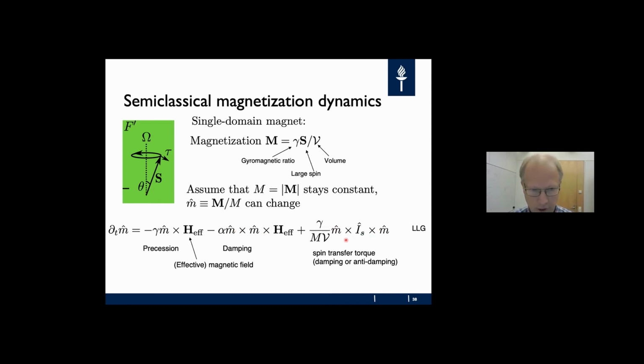And then the last term was added by Slonczewski, and it describes the spin transfer torque from a spin current from an adjacent magnet. It can describe either a field-like torque or a damping-like torque that you can get from this.